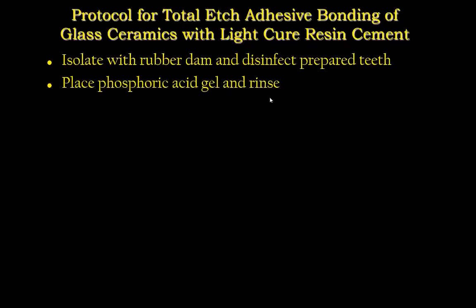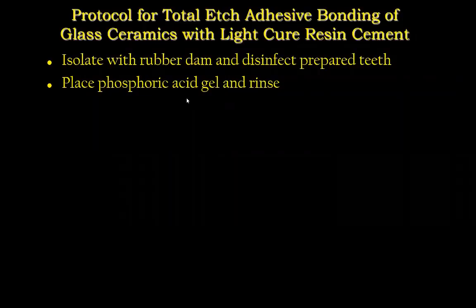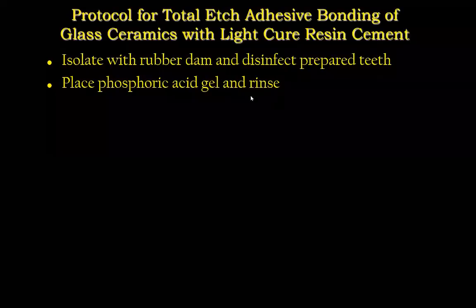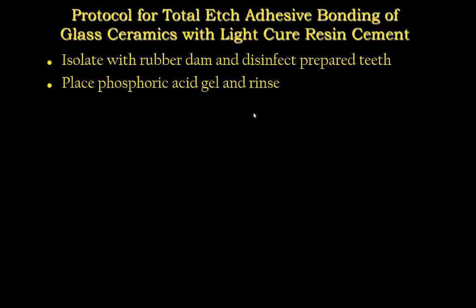So we place the phosphoric acid gel on the tooth. If I'm doing 8 teeth, I'll etch 4, rinse, etch 4, rinse. If I'm doing 10, I'll etch 5 and rinse, etch 5 and rinse. Especially if it's all enamel, 100% enamel I'm bonding to, I don't care. I'm not worried. It could be on there 10 seconds, 15 seconds. It could be on there 30 seconds. It's not going to hurt. But you don't want to over etch dentin. So if I have some dentin exposed, I really don't want it on there more than about 15 seconds. So I'm going to etch only half the arch and rinse that off in the same order that I etched.